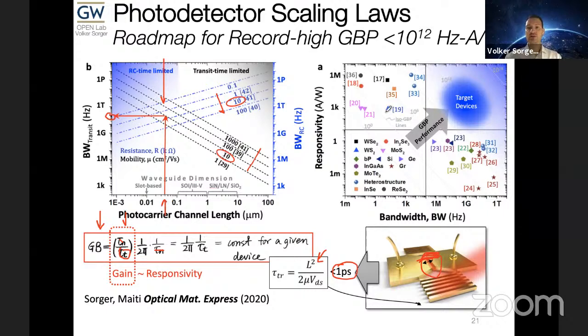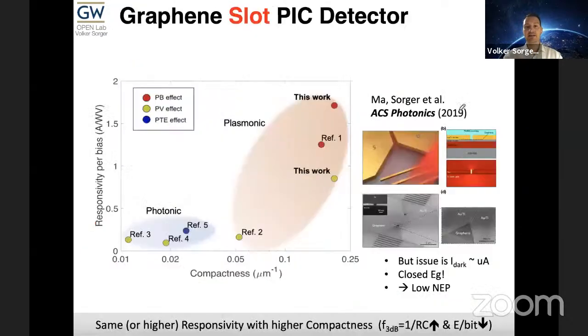And on the right here, we're showing the gain or the responsivity versus the bandwidth for all devices that are either slow and sensitive or fast but not sensitive. And with this, we are now pushing into this sensitive and fast regime. And here's an initial work in this direction using graphene, where we show the responsivity versus compactness in these plasmonic slot structures shown on the right. This is work from this group.